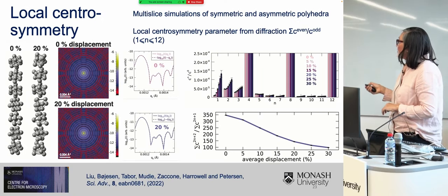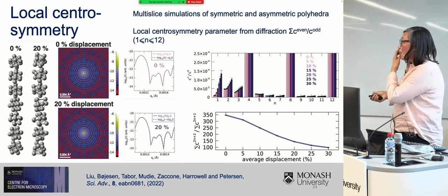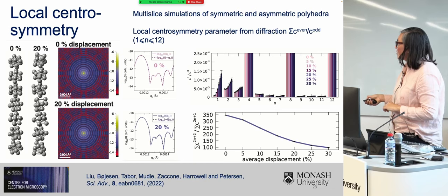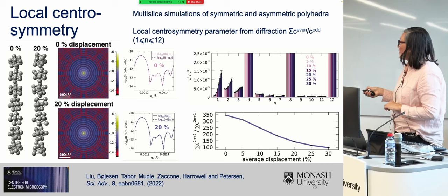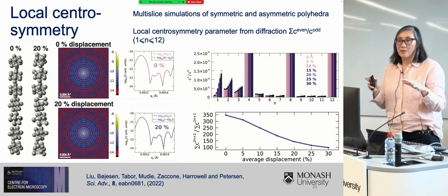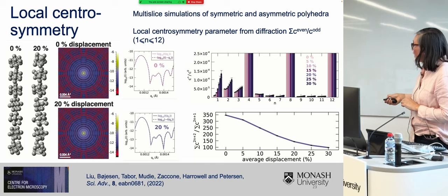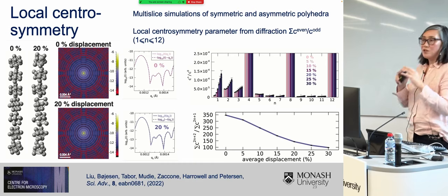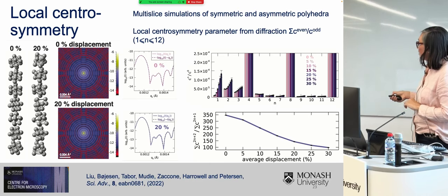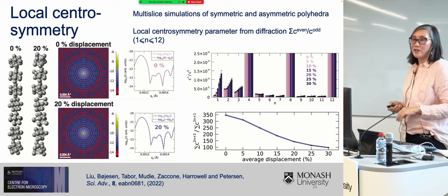And so I tested this idea out by using simulations. So here you can see for symmetric polyhedra, the diffraction pattern retains Friedel symmetry. So here I'm plotting the log of the intensity as a function of Q versus the intensity as a function of minus Q. But if I introduce some random displacements so that the centrosymmetry of the polyhedra are disrupted, then you can see that the pattern breaks Friedel symmetry. And then if I do this, averaging over many different configurations, you can see that my centrosymmetry parameter here actually decreases smoothly as the symmetry of the configurations is reduced.